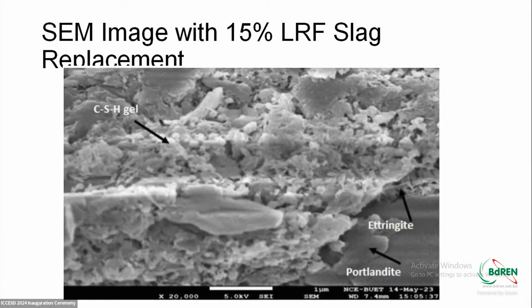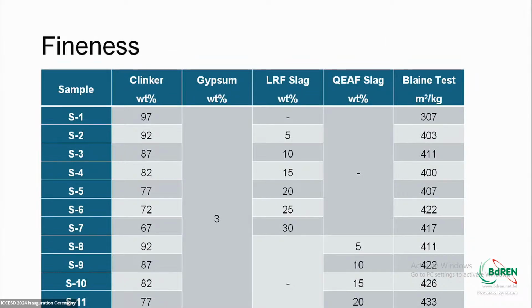Similar effect is found. Now, after that, we tested the cement mortar with cement fineness. Ultimately, after mixing, fineness increased with the replacement of both LRF slag and EF slag, and that's quite natural because the powder form of LRF slag and EF slag was much finer compared to clinker. So fineness was higher.